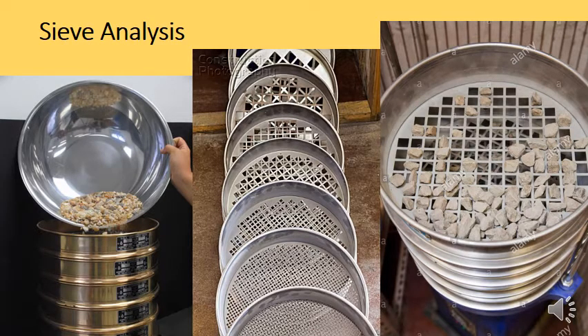Now this is an example of the sieves used in the sieve analysis. So you can see there we've got sieves which are all different size openings, and we arrange them on the machine. We stack them up, the largest opening on top, the smallest opening on bottom, and we put our sample inside the top, and then we vibrate it. And then you can see the final sample. It's got the biggest particle stuck in the top sieve, and the smaller ones will be falling down.